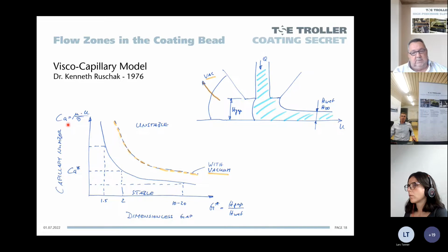The capillary number is like the Reynolds number, for example, in flow mechanics or fluid mechanics, a comparison between different forces. The capillary number compares viscous forces with speed, or in other words, inertia forces, and surface tension forces. And what you like to do is increase the coating gap, but according to this diagram, it's not allowed for each capillary number to use a large ratio. So, for example, if you have a ratio of 2, the referring capillary number is quite low, and when you calculate the capillary number, and this is maybe somewhere here, then you have to decrease the coating gap. And with a vacuum box, you can shift the transition line towards higher gap ratios.